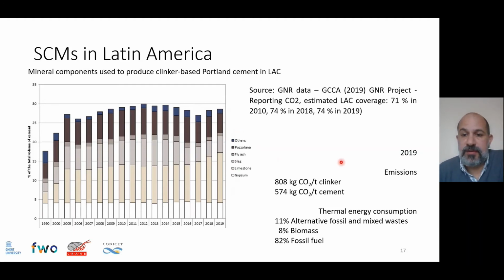Nowadays, the Latin American industry has achieved a specific emission of 808 kilograms of CO2 per ton of clinker, and due to the high replacement ratios, the emission of cement is 574 kilograms of CO2 per ton. Also, the thermal energy consumption has been improving during the last years, with more use of alternative fossil and mixed wastes, and also biomass. But of course, there's a long way to go so we can achieve carbon neutrality in 2050.